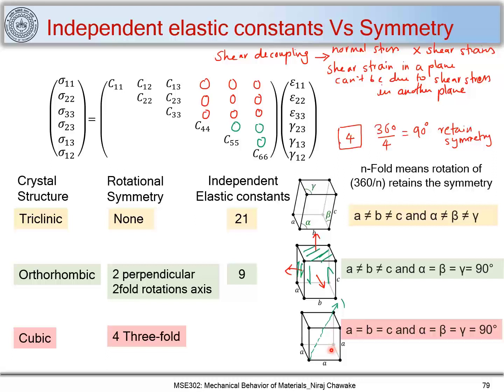Because of the cubic symmetry — the highest symmetry — consider the following responses. When I apply only σ₁₁, I get ε₁₁ related through C₁₁. Similarly, applying only σ₂₂ gives ε₂₂ related through C₂₂, and applying only σ₃₃ gives ε₃₃ related through C₃₃. Because of the nature of the cubic crystal structure, C₁₁, C₂₂, and C₃₃ must all be equal.